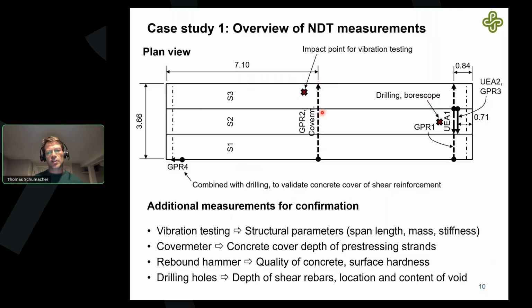I did take other GPR measurements. We did one over here too to determine the shear reinforcement and the cover of the shear reinforcement. But the images you'll see will be focused here. So here is where I did measurements both from the bottom of the bridge, but also from the top. What we wanted to make sure is that we have great confidence when we get these images, these cross sections. So we did some additional measurements.